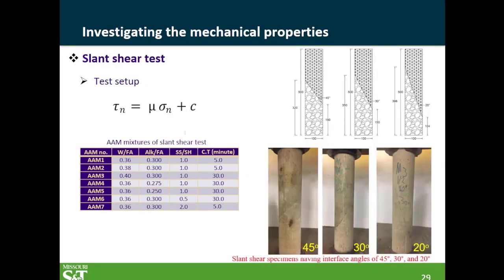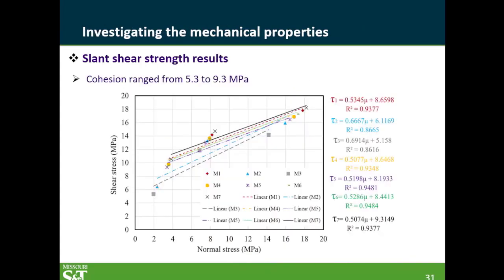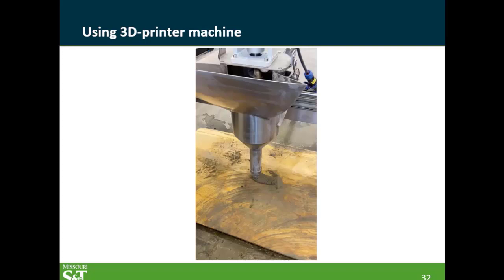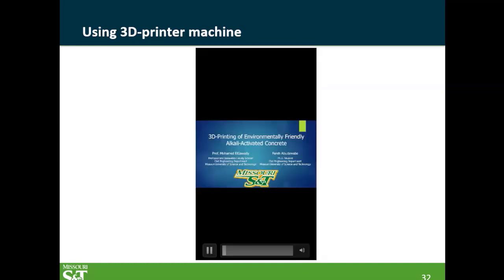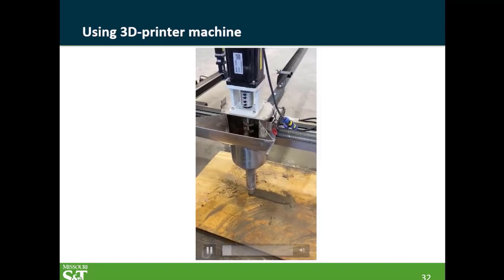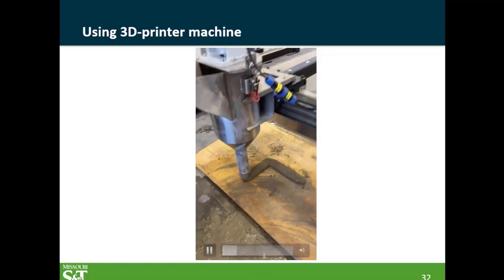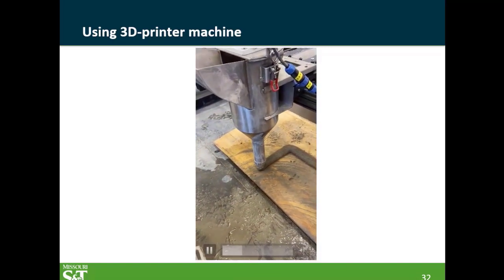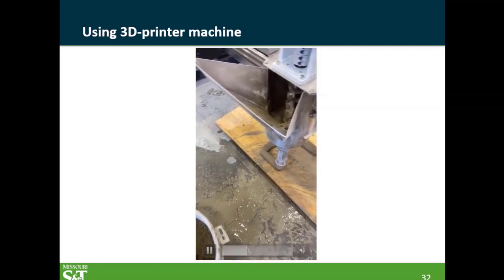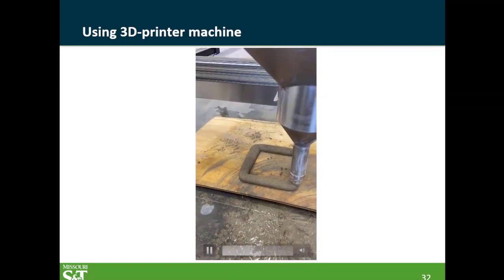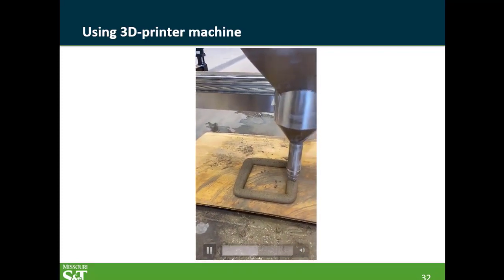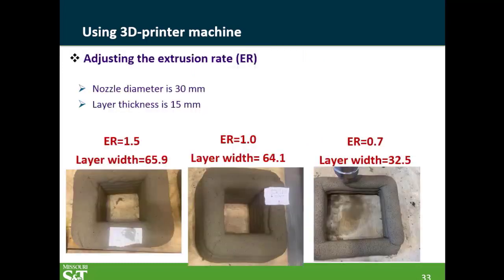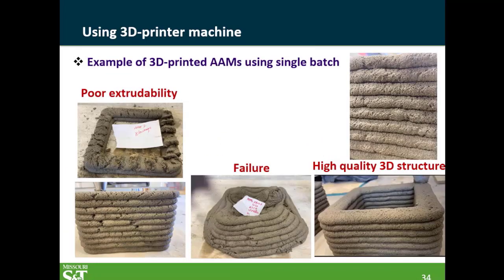We also did slant shear between the different concrete mixtures. And then based on all this, we end up with printing the mixtures. And when we did the printing, we did some really well-working mixtures, and also some specimens that we said would fail, just to ensure that things would follow whatever we developed. So as I mentioned, you can see some of those failed, and based on our criteria that we developed, they should fail.